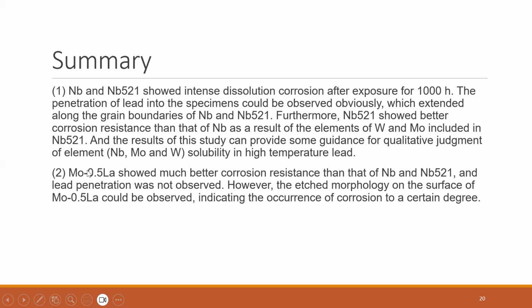Two, molybdenum alloy showed much better corrosion resistance than niobium and niobium alloy, and lead penetration was not observed. However, the etched morphology on the surface of molybdenum could also be observed, indicating the occurrence of corrosion to a certain degree.